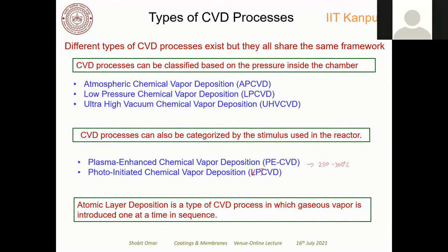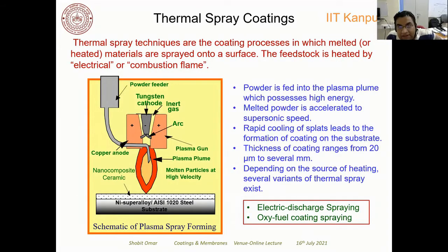I will continue. Okay, so another type of technique which is very important is thermal spraying technique. This technique is not a vapor deposition technique. In this technique you basically melt the powder that you have, and that melting will be done either through plasma, or by supplying thermal heat through a combustion flame. Okay, and this liquid powder or melt is then deposited on the substrate, right? And you will have a uniform microstructure. And I will talk about this plasma spraying when we talk about the thermal barrier coatings, right?